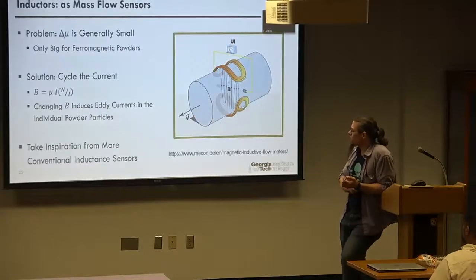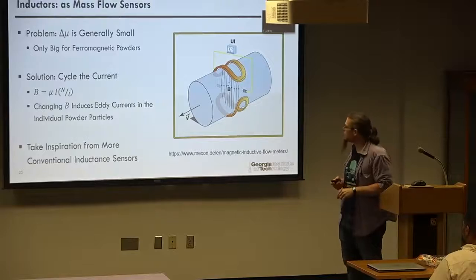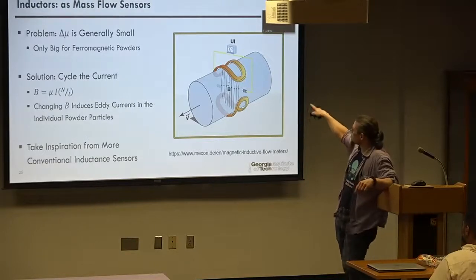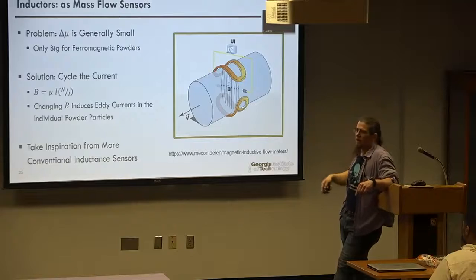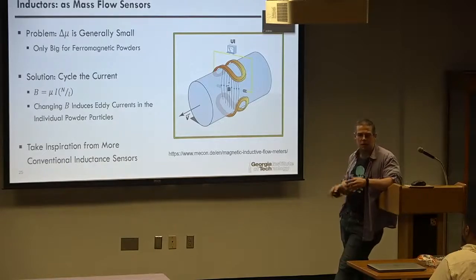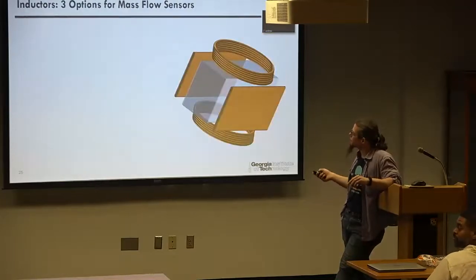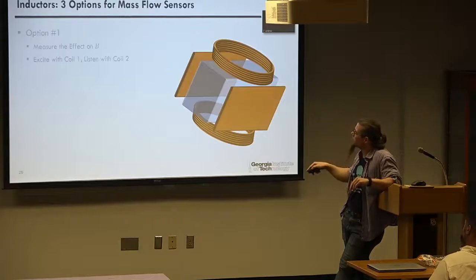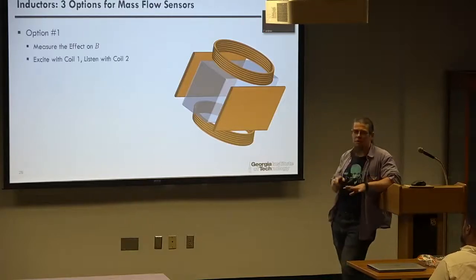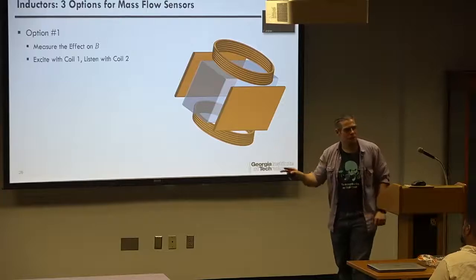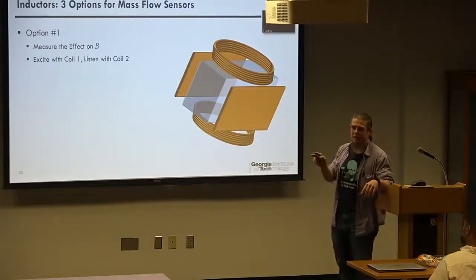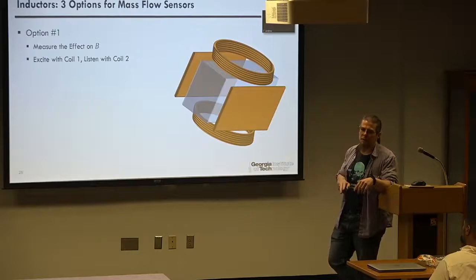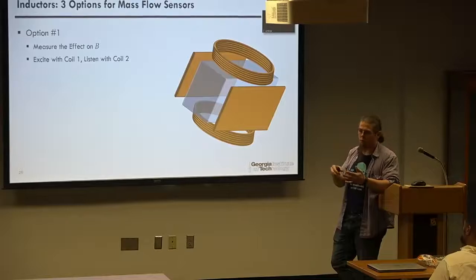We're going to take inspiration from more conventional inductance sensors for liquid flows, where we have two different coils, and then we have a way of measuring essentially a potential difference, either plates or pins across that flow where the magnetic field is exciting it. So here's what generally the sensor system would look like. We're looking at three different options here. When we created this setup, we realized there are three different ways that we can excite it and measure what's coming out the other side. We expect the sensitivities to be different. We don't know if they will be different for the different powder flows or if they will uniformly be different, in which case we just pick the best one and run with it.